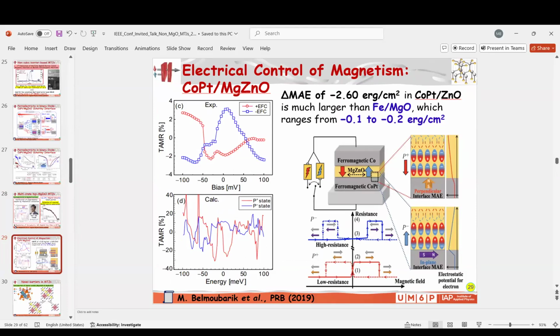Without going into a lot of detail, because of the ferroelectricity and the change of the charge at the interface, we could induce a large delta MAE of 2.6 erg per square centimeter, which is far bigger than the case of iron MgO. So, in short, we could enhance the PMA performance at these interfaces.